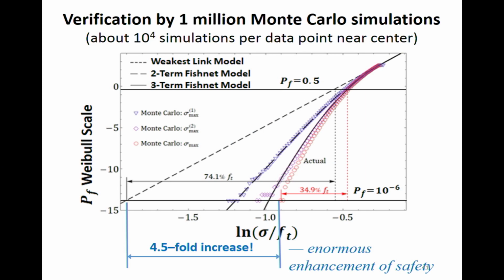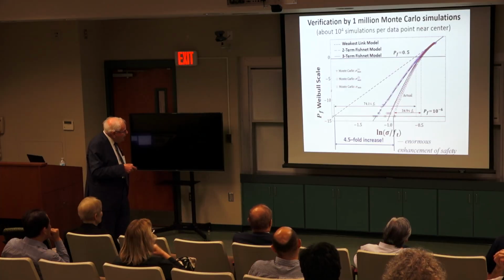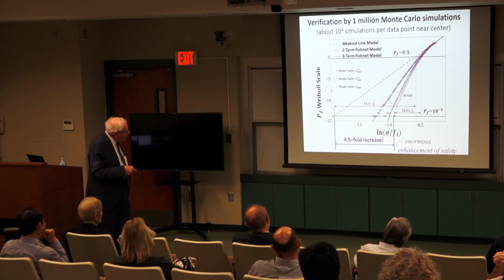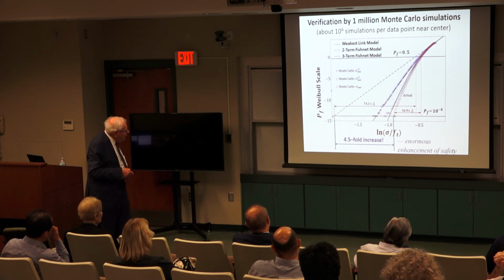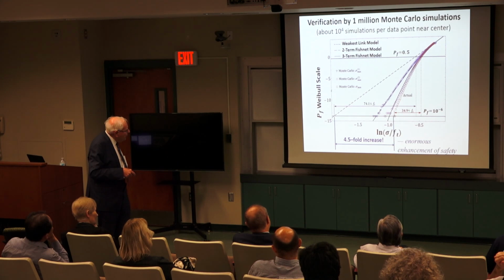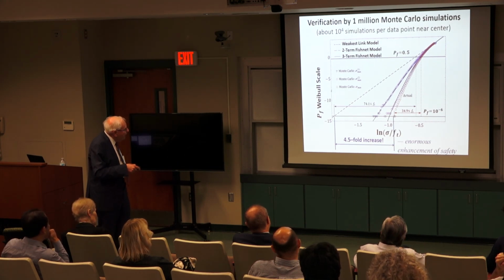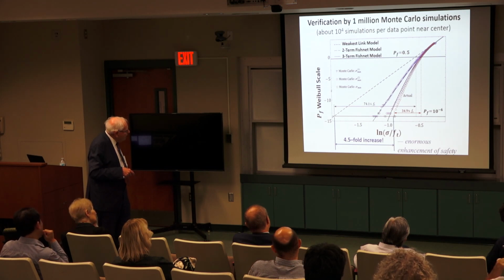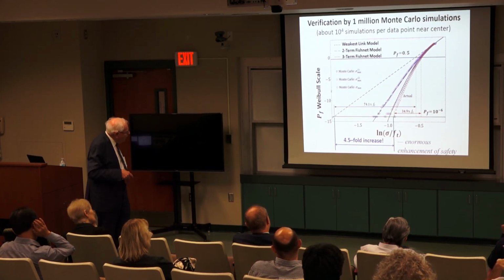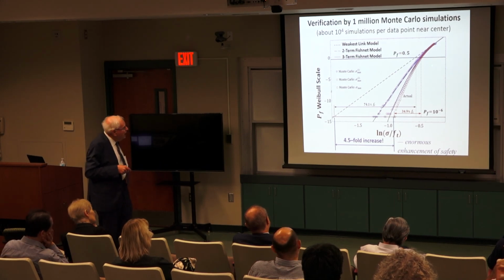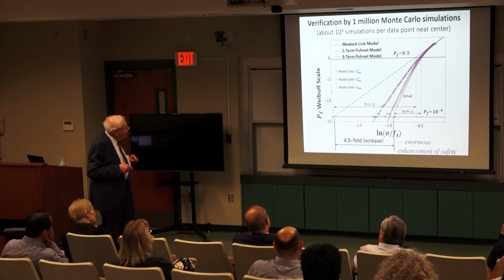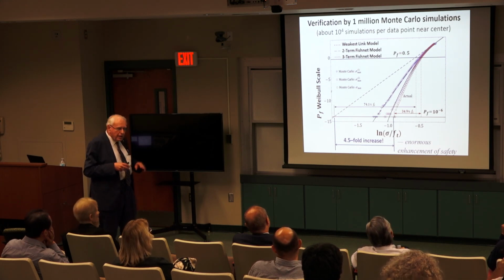This is again the line of 10 power minus 6, and you see the enormous saving. So if you compare to the weakest link model, okay, a positive geometry structure failing because of one element, you get this. If we can induce the fishnet action, meaning this alternating series parallel, you get from from 74.1% to 34.9% in terms of safety. It's a 4.5-fold increase, an enormous enhancement of safety. What I leave out at this point is that this is the median, the mean is somewhere here. There is another degree of safety, of course.